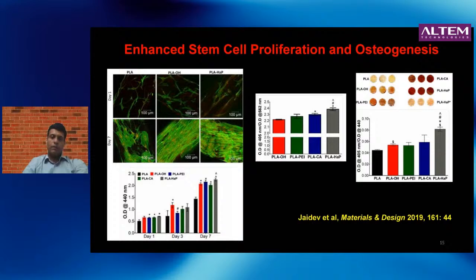Actually, we procured them from someone who had isolated them from human bone marrow, and we seeded the cells on the scaffold, either the as printed scaffold itself, or the scaffold that had been treated with the NaOH to introduce OH groups and make it more hydrophilic, and the final hydroxyapatite coated scaffold. And then what we did was to look at how the cells were growing. Here we've zoomed into an individual strut of that scaffold. And you can see one day after seeding the cells, they look more or less the same, some cells on the struts of the scaffold.